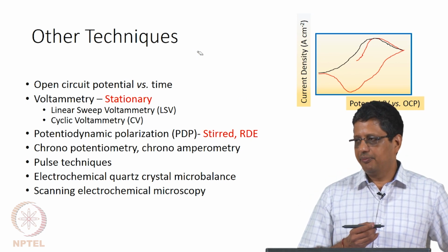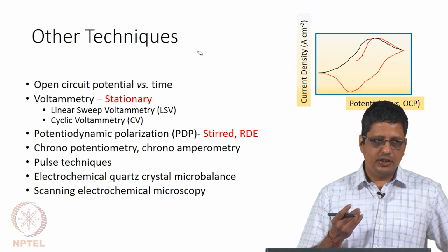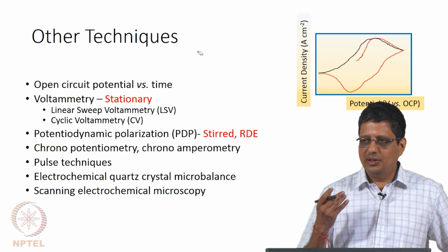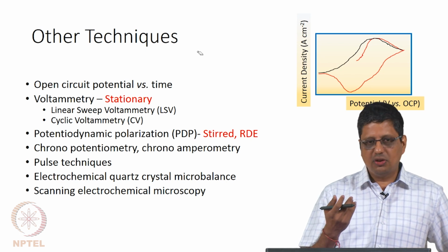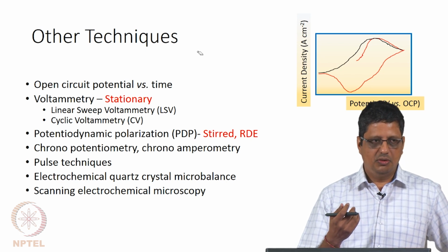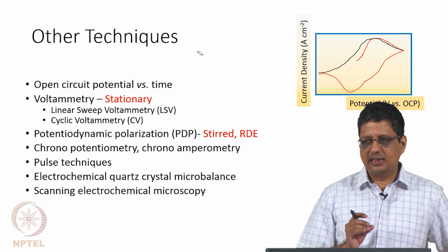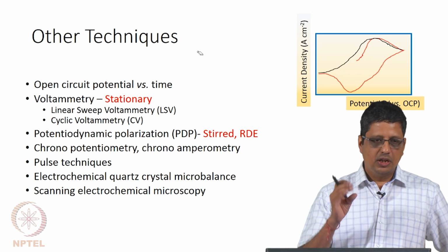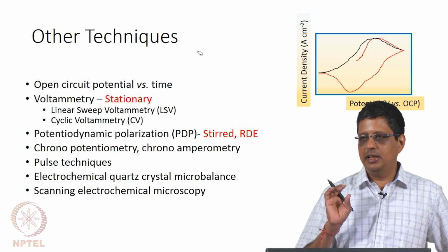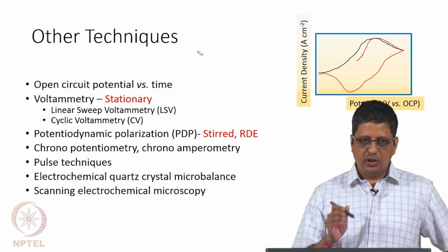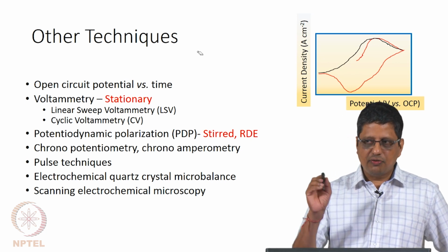by half. Okay. And if your dissolution is very fast, large dissolution occurs, you do not want to conduct the experiment for a long time because the electrode will dissolve fast. So, you want to conduct for a short time, and at that condition it is okay to have little faster, because you are dissolving fast, the total current is mostly going to be reaction current, very little will come from double layer.